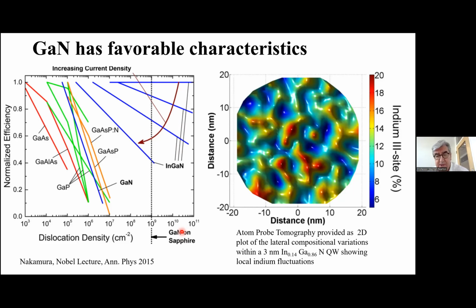And it was really because when you grow an InGaN quantum well, it has compositional variations within it where the indium-rich regions provide localized quantum wells, so you get good carrier confinement and good light emission. So that was an advantageous thing from nature, that this material system was very robust against having high dislocation density, because, as I said, there was no substrate at that time.